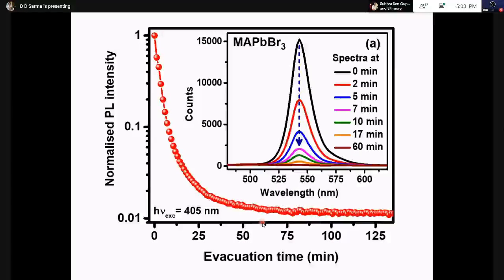What is believed to be going wrong is that as you evacuate, actually two things can happen. For doing this measurement, I'm evacuating, so it could be evacuation time, but also I'm shining light on the sample. So maybe shining light is degrading my sample. So this time, which I've written as evacuation time, is actually both evacuation time and exposure time of light. How can I separate the two out?